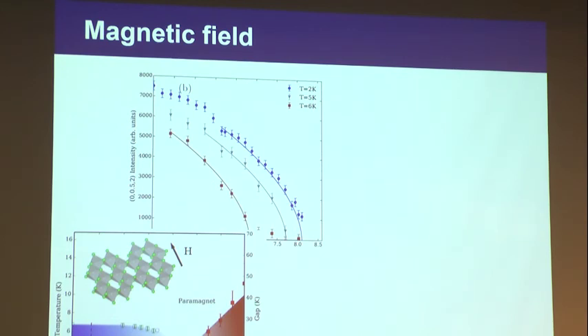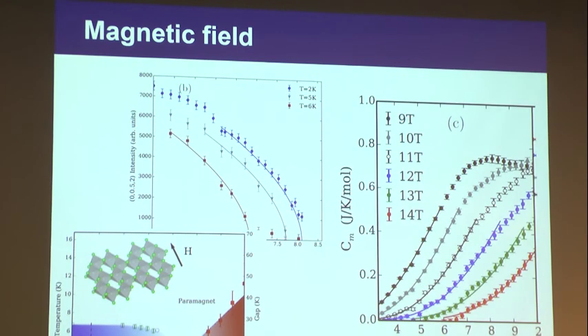Above this magnetic field, if you continue to increase it, you are creating an energy gap in the system. You can probe the energy gap by doing specific heat measurements, because if there is an energy gap, then there is exponential suppression of magnetic specific heat at low temperature. So here are 9 Tesla, 10 Tesla, and 11 Tesla. As you increase the magnetic field, the gap size increases. So you can plot the magnetic energy gap as a function of magnetic field on this side, and you can see that it goes down to almost 0 somewhere around 6 to 8 Tesla.